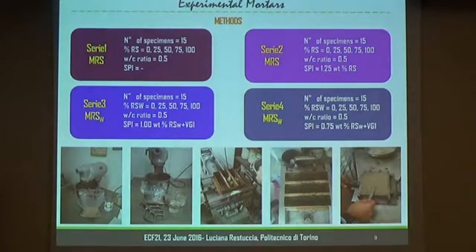The work was done in consecutive steps, and so we cast 4 series in which some parameters were kept constant. For example, the percentage of replacement, so 25, 50, 75 and 100%, and we also kept constant the water to cement ratio equal to 0.5. We only varied the amount of superplasticizer in our experimental casting of mortars.